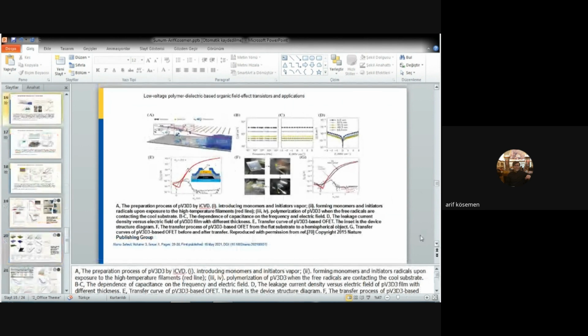And this is one of the other examples from the literature. In this study, a PV3D3 dielectric polymer material was used as an insulating layer, and with this they can get low operation voltage transistors that can work under 3 volts.